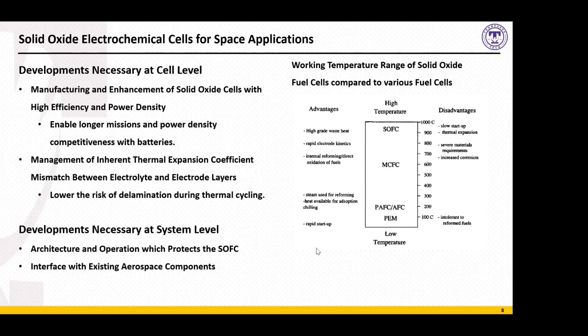And we also need to think about the management that is inherent to the thermal expansion coefficient mismatch between the electrolyte and the electrode layers. So again, we want to lower the risk of delamination through thermal cycling. So these will be two objectives at the cell level.